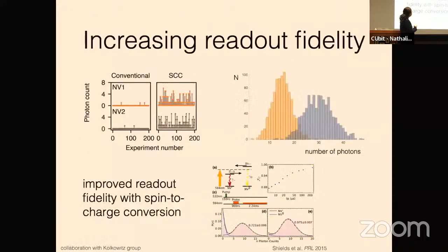Now, the problem is that with NV centers, normally you get extremely few photons per shot. So it's something that people don't like to talk about because it doesn't sound great, but you basically get something like 0.03 photons every time you run an experiment. Now, you can run these experiments every 10 to 20 microseconds, so you just average 1 million times, and that's how you do these really beautiful quantum measurements with NV centers.